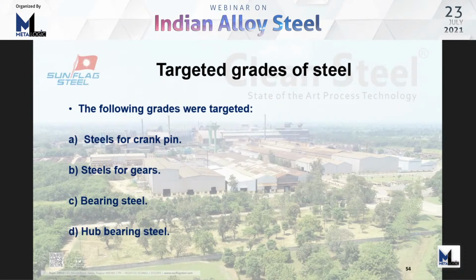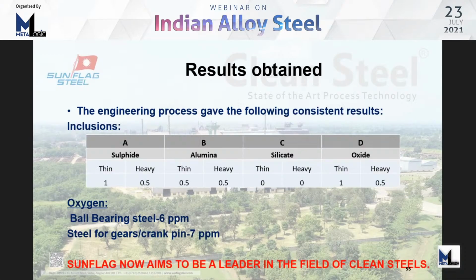Now the following grades were targeted: steel for crankpin, steel for gears, bearing steel, and hub bearing steel. These are the results which we have achieved consistently, and these are in about 75-80% of our steels. These results are obtained in these grades. Oxygen we have achieved ball bearing steel 6 ppm and steels for gears and crankpin 7 ppm. Sunflag now aims to be a leader in the field of clean steels.